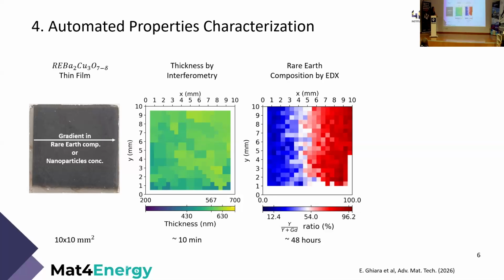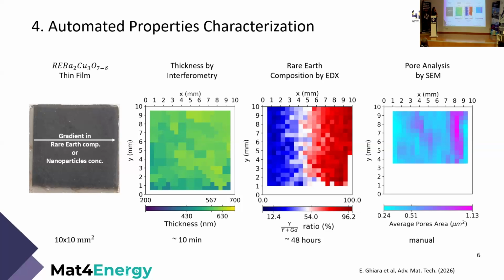SEM here downstairs, which is a really tricky measurement, since to detect the rare earth in the thin film is not so easy. It lasts more or less 48 hours, but luckily, being automated, we can perform this during the night. At the same time, while the EDX is running, we can also acquire the SEM images for doing surface morphology analysis, although this is not always so straightforward because the focus needs to be always corrected manually. So this is something we can still improve regarding the automatization of the surface morphology.